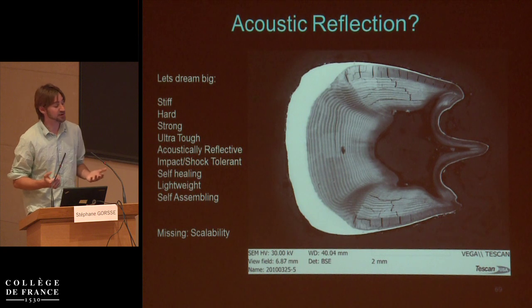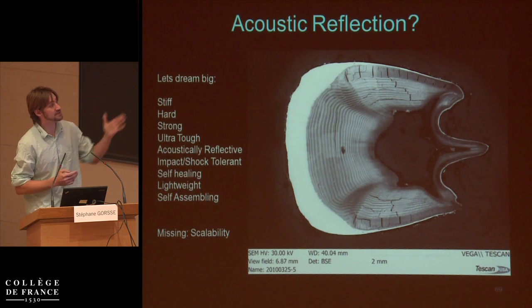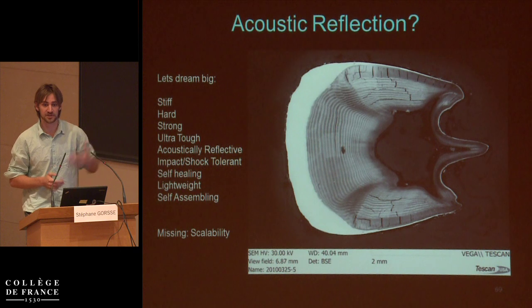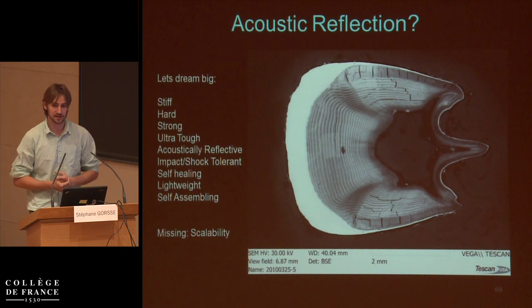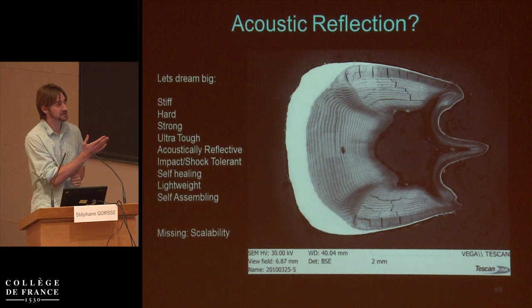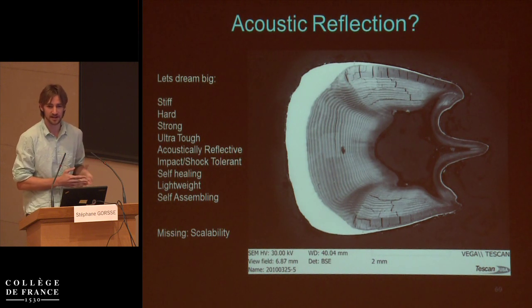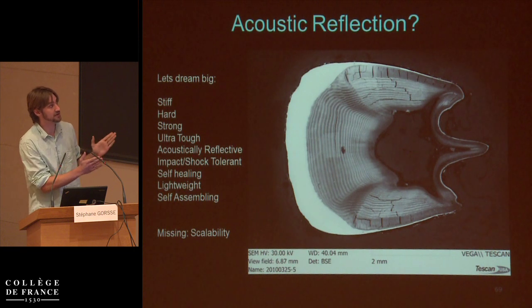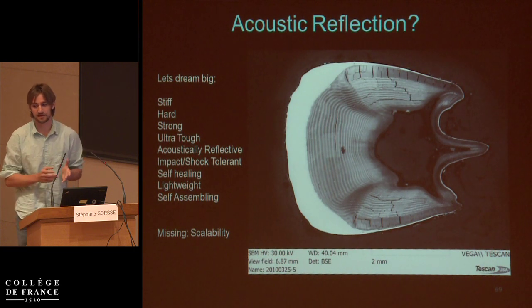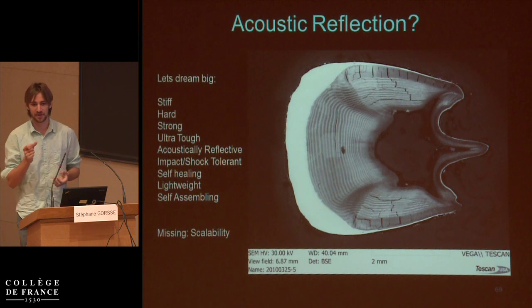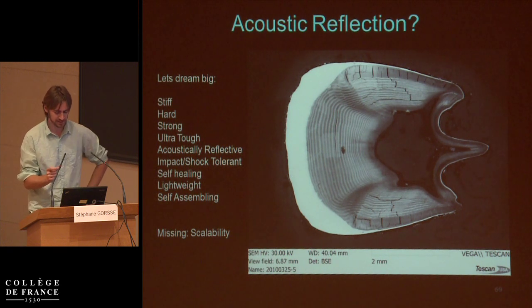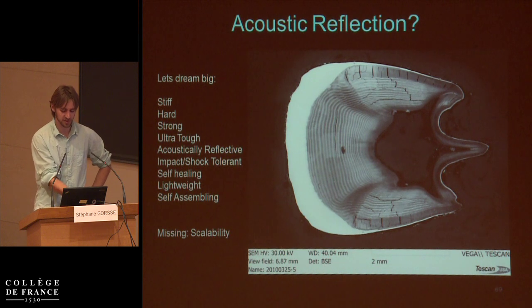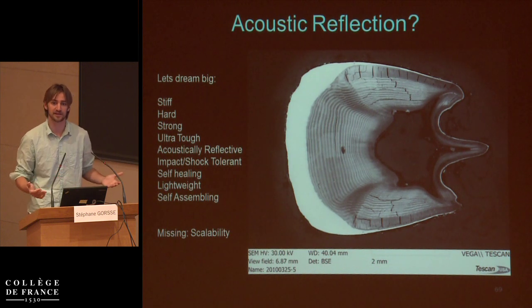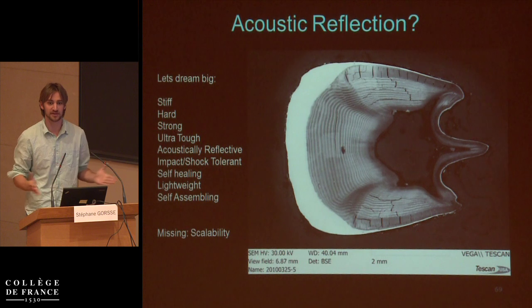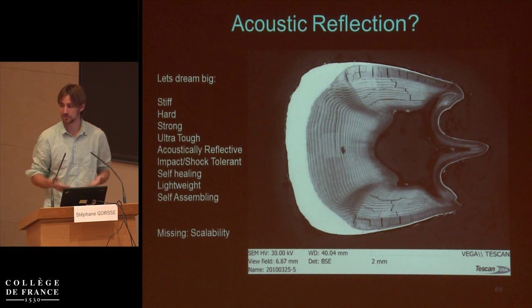And so I don't know if it's going on, but it would be amazing if that were the reason for this puzzling gradient in the pitch that we don't really see in most systems, where this helicoidal motif is ubiquitous, but a graded helicoidal motif is not, especially a gradation of this large. But the acoustic band gap created by a helicoidal composite is, again, proportional to the pitch. And so by grading the pitch, you can extend your band gap, and the amount of forbidden waves that could pass into this material would be vastly broadened.